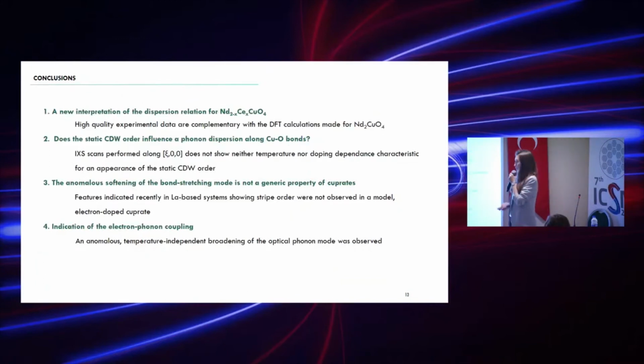So to summarize my presentation, I've presented a new interpretation of the dispersion relation for the model electron-doped cuprate NCCO, and our interpretation agrees quite well with DFT calculations. I'm also saying that the static charge density wave order does not influence the dispersion of phonon modes. There is no temperature nor doping dependence that is characteristic for a charge density wave order. I'm also saying that this anomalous softening of the bond stretching mode is not a generic property of all cuprates. It was observed for striped order systems, but it wasn't observed for any other system where the stripes are not present. And we see in our studies some indication of electron-phonon coupling that possibly is caused by dynamic charge density wave order coupled with paramagnons.